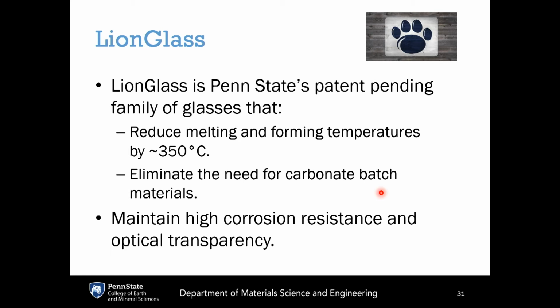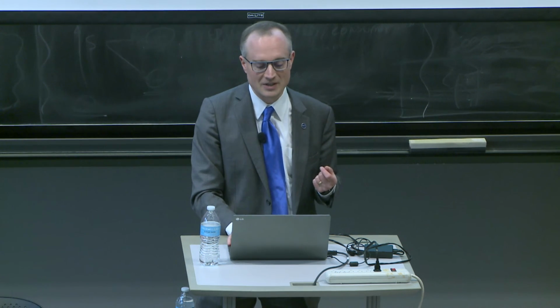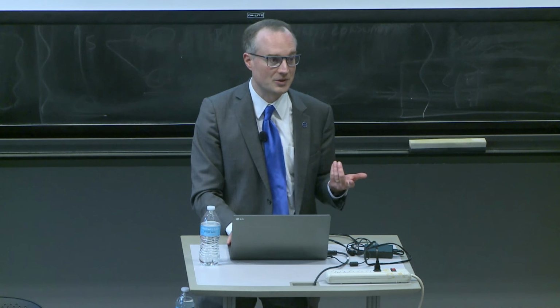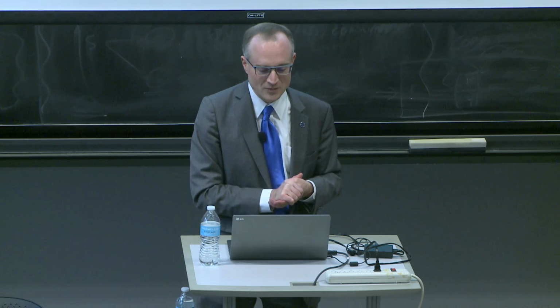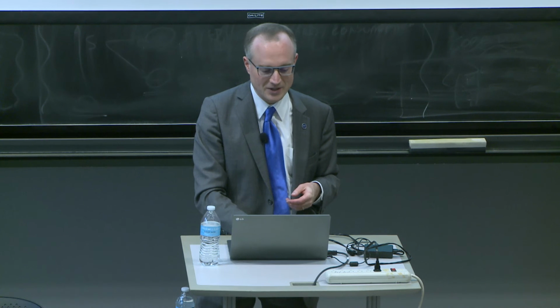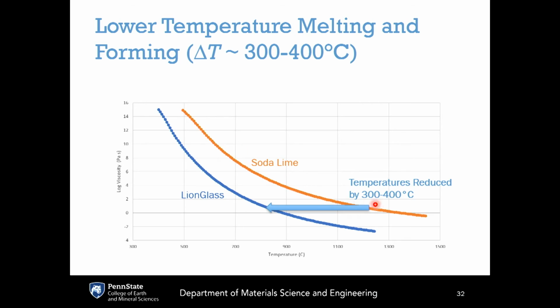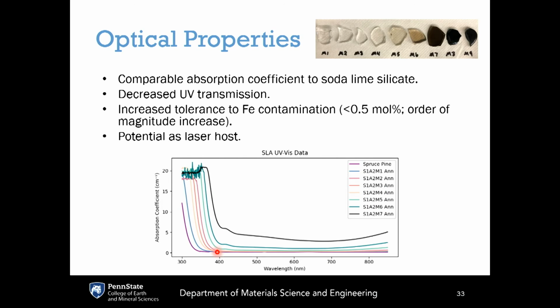Traditionally, the problem with many low melting temperature glasses has been poor corrosion resistance, where they just suck up the humidity from the environment and degrade pretty quickly. But this glass has corrosion resistance that is at least as good as soda limes, and also outstanding optical transparency. So this shows the log viscosity curve versus temperature for traditional soda lime silicate glass, and then for our new family of Lion glass, which is shifted down by about 300 to 400 degrees C. Optically, it is beautifully transparent here, and actually even more transparent than soda lime silicate.